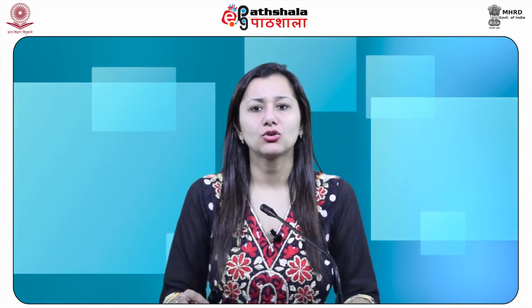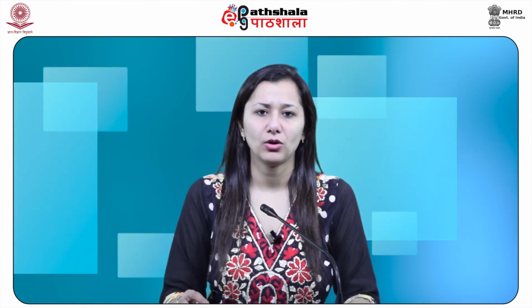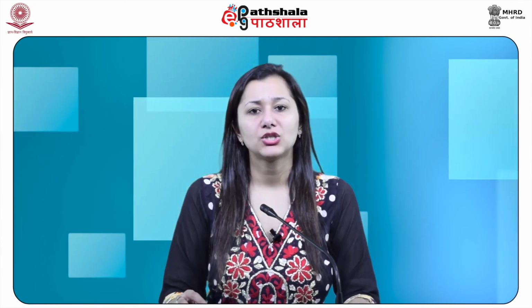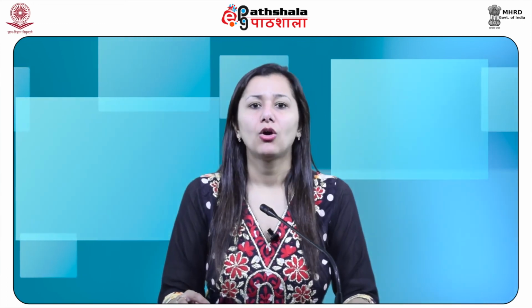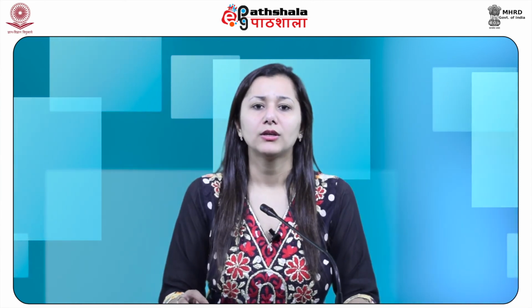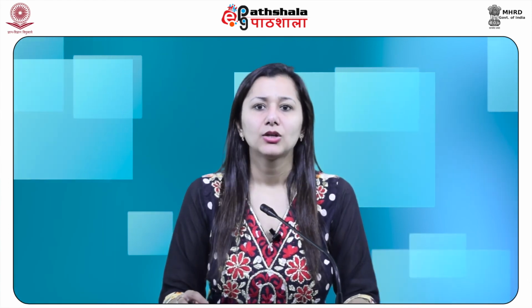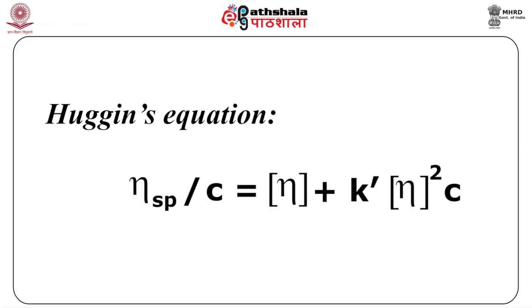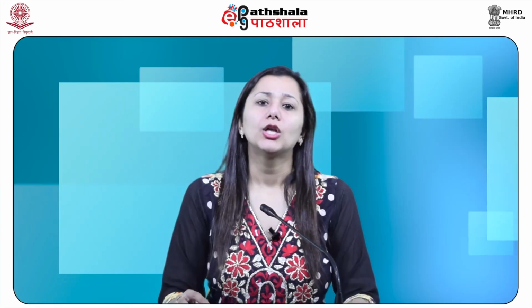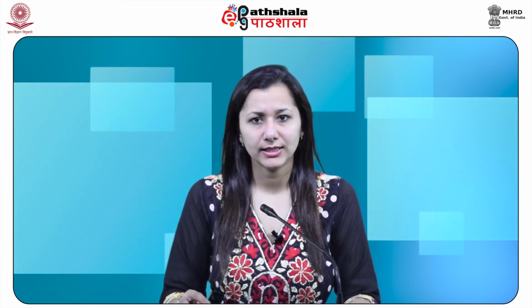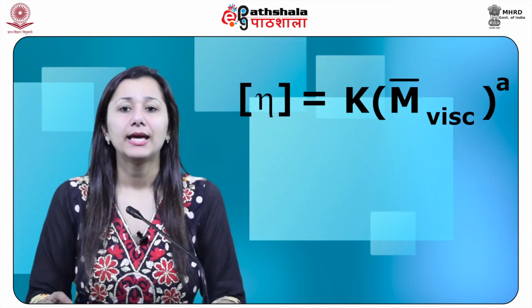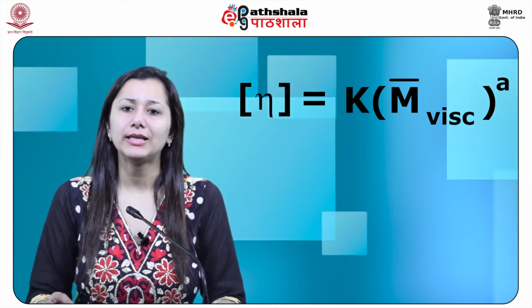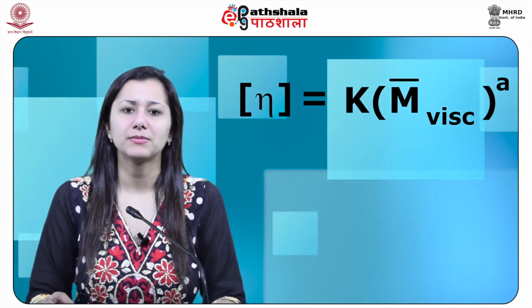Solution viscosity is a measure of the size or the extension in space of polymer molecules. Dilute solution viscosity is generally measured in capillary viscometers such as Ostwald-Fenske or Ubbelohde viscometers. Viscosity data as a function of concentration are extrapolated to infinite dilution using the Huggins equation. The Huggins equation is η_sp/C equals [η] plus k′[η]² times C. The alternative definition of the intrinsic viscosity leads to the equation given by Kraemer as ln η_relative/C equals [η] minus k″[η]² times C.